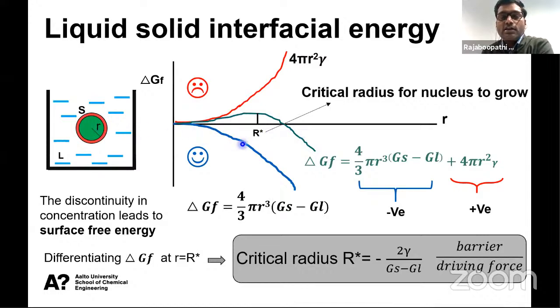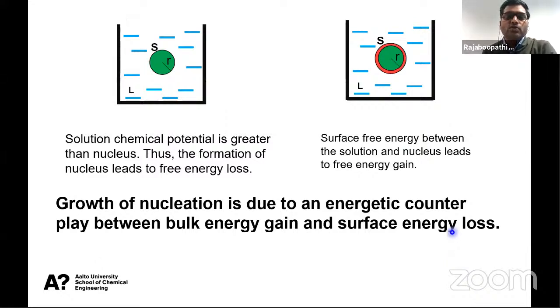When the nucleation cluster reaches a critical radius, the crystal will start to grow. And this is the total Gibbs free energy of the system. When you differentiate this equation at r equal to r star, you can get the critical radius. After reaching the critical radius, the nucleus forms a crystal. So this Gibbs free energy is actually a barrier in crystal growth, and we need some driving force to get bulk crystals. We can say simply that crystal growth is a competition between the surface free energy and the bulk energy term. The bulk energy term we get from the chemical potential. If the Gibbs free energy barrier is very high, you cannot get any crystals, because the nucleation cluster won't reach the critical radius.